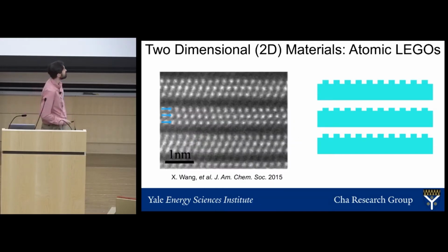So here's an example of 3 layers of a material called titanium carbide. This is a transmission electron micrograph. So what we're actually seeing, these white dots, are actual individual titanium atoms. As we can see, each layer has 3 titanium atoms in it, and it's very difficult to see in this image, but there's actually 2 carbon atoms above and below the central titanium atom, which means that this layer is 5 atoms thick. And we can see here 3 layers stacked on top of each other.